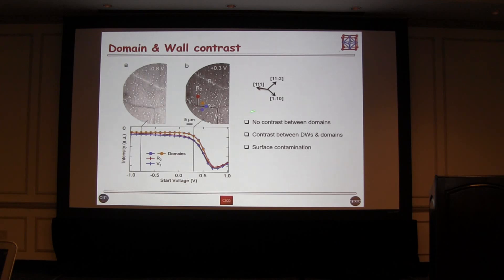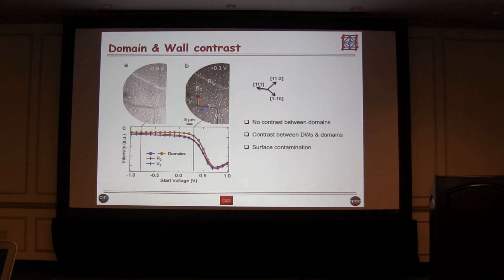The first mirror electron microscopy images are taken at a very negative start voltage, so electrons do not interact strongly with the sample surface and are reflected before getting there — the contrast is not very high. First, if you look at adjacent domains, there is basically no contrast in intensity between two domains — this is what you expect from strontium titanate, a non-polar material. However, there is a clear contrast between the domain walls and the adjacent domains.